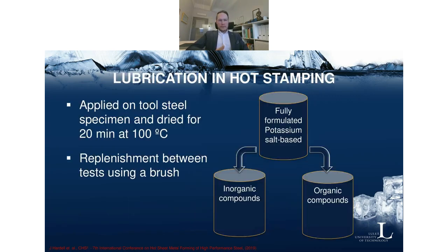If we move on to hot sheet metal forming and lubrication for that process. Now this, I should mention that this process is typically performed in dry conditions. So traditionally, the industry has not been using any lubrication in this process. So basically you have your hot sheet that goes into the tools and you form it in hot and dry conditions. We set out to investigate whether lubrication can provide some alleviation to this material transfer problem.